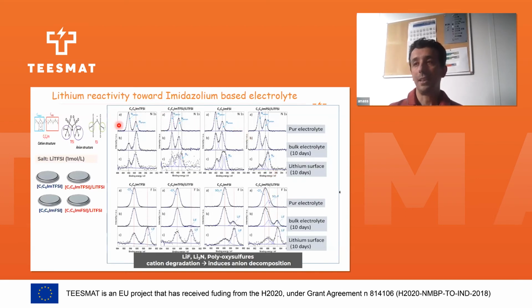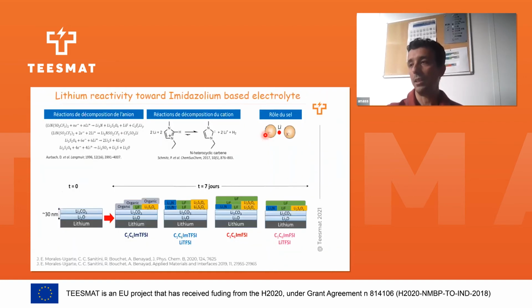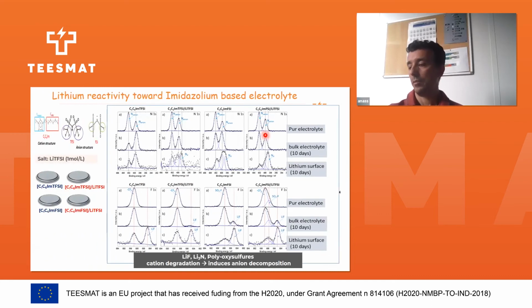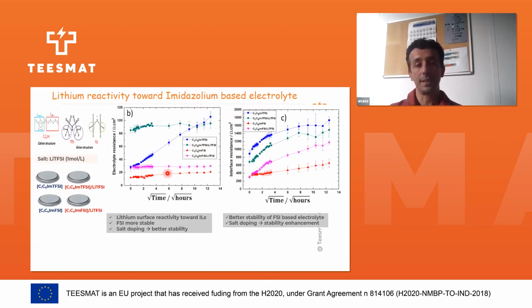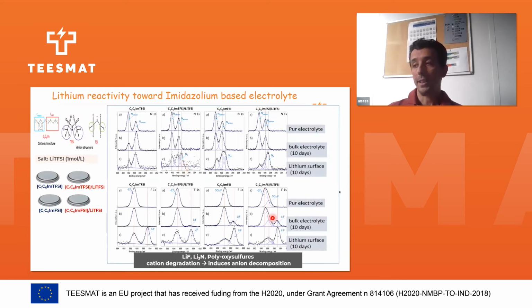This is for TFSI, but in the case of FSI, we have less degradation, which can be linked to the stability of this kind of electrolyte. We did the same thing for fluorine, because fluorine is one of the components of our electrolyte. We can see, for example, for this combination, degradation of this LiTFSI-based electrolyte with the formation of LiF, which is the case for other electrolytes, but in different proportion.